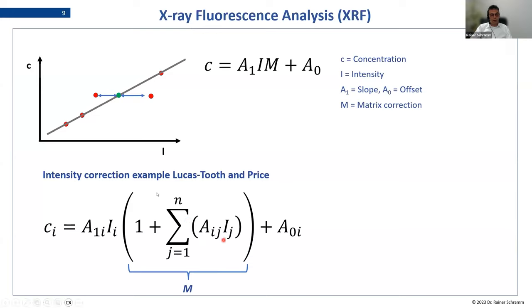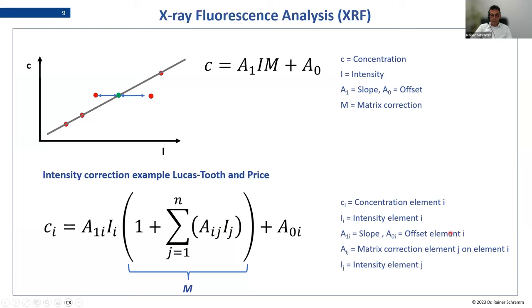If we have these cases, then we need a correction. And therefore, the disturbing elements are introduced. So that means the intensity of iron, which excites the chromium, or titanium, which absorbs the chromium, is introduced. That means we measure also iron and titanium. And then there is a factor calculated to get these two factors either higher than one or lower than one. And this is done based on standard materials.